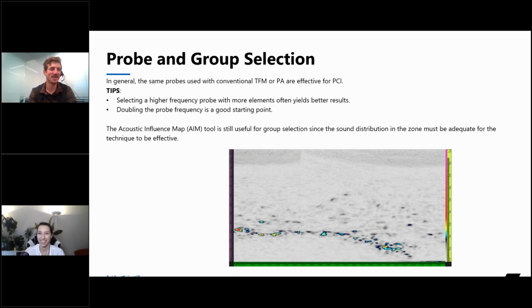So moving forward, I'm just going to discuss some of the probe and group selection rules or best practices that we want to use with PCI, because there's a few changes from our standard amplitude-based techniques that we want to apply in order to have the best results as soon as possible. In general, some quick tips: we want to use a higher frequency probe with more elements to yield the best results. And in general, we want to double the probe frequency from our standard inspection. So if we normally use a 5 megahertz probe, we want to move into something that's a 10 or a 7.5 and vice versa.